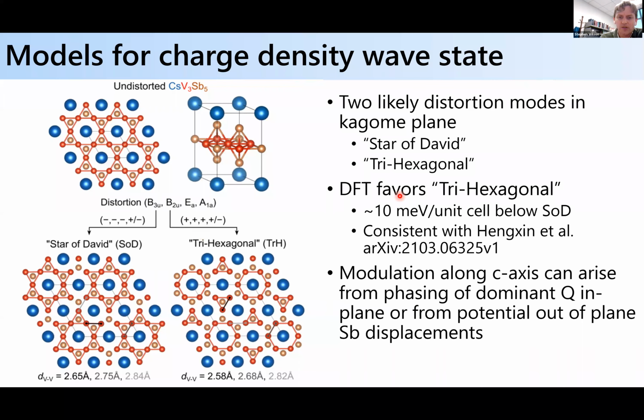Okay, so Sam's DFT calculates that the trihexagonal state should be favored by an order of 10 millielectron volts per unit cell. This is consistent with some work that was put out at the same time, actually posted before our work.